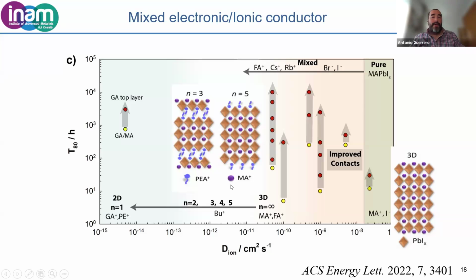And of course, the other way to improve the stability of the device is improving the contacts. So if we take a single formulation and then improve the formulation of the contacts, we will see a vertical displacement for this formulation, meaning that the devices get more and more stable. And this is because the contacts are not reactive with the migrating ions. And there have been loads of people in the field working on this.